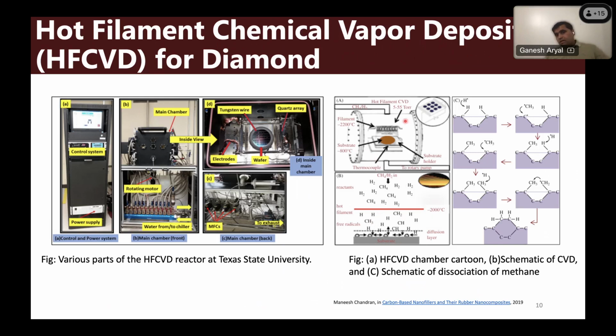In the chamber, the hot filament we use is tungsten wire, and the heat is generated on that wire by applying some voltage and current. The wire gets heated based on the Joule heating effect. Based on the dissociation of carbon and hydrogen from methane, we get the diamond. There is also a good chance of forming graphite instead of diamond, so there is a window region of conditions that we have to follow to get diamond, with sp3 bonding of the carbon.